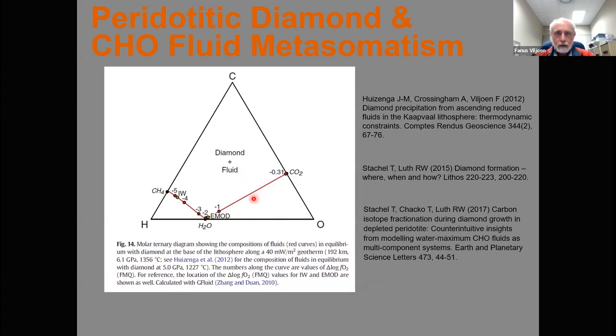However, depending on compositions and as the temperature changes, as these fluids move through the lithosphere from the high temperature environment into the lower temperature environment, in that flow along the geothermal gradient, you potentially crystallize diamond from these fluids. And so if you have pulses with time, with geological time, for whatever reason, of these fluids, you progressively crystallize diamonds that then become progressively bigger and bigger as they have more contact with these fluids over geological time.